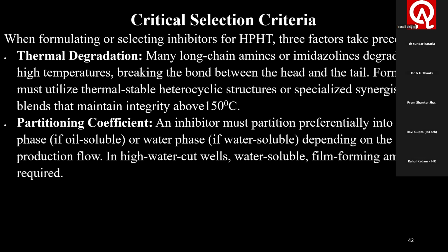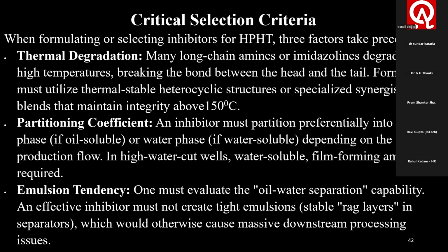partitioning coefficient. An inhibitor must partition preferentially into the oil phase if oil soluble, or water phase if water soluble, depending on the production flow. In high water cut wells, water soluble, film forming amines are required. And last is the emulsion tendency. One must evaluate the oil water separation capability. An effective inhibitor must not create tight emulsions, that means stable rag layers in separators, which would otherwise cause massive downstream processing issues.